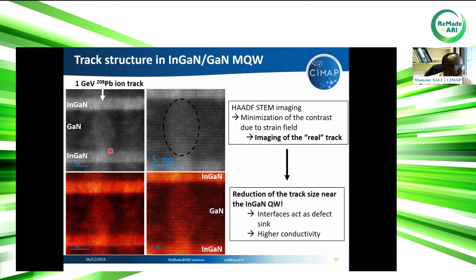But when we look at the track structure in this multi-quantum well indium gallium nitride, okay, it's not really clear here. This is a STEM HAADF image. If you know a little bit about TEM, in this case we use very small camera lengths, which means we only collect electrons that are at high angle. So this imaging mode is not sensitive to the strain field created by tracks. So what we observe here is a track.